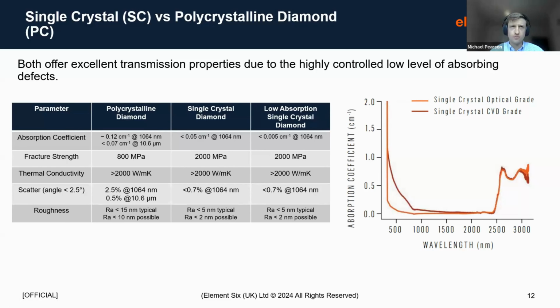The difference in performance between your single crystal and your polycrystalline materials is going to be very minimal. And just to give you a sense of what sort of scatter we'd expect. For polycrystalline material at 1064 nanometers, we'd expect typically about 2.5% scatter. For our single crystal grades, that'd be down to about 0.7% scatter.